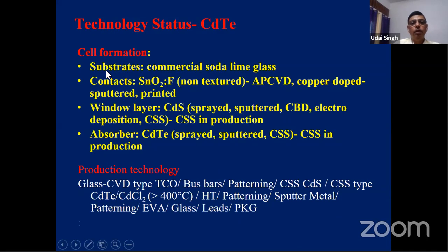So for cell formation, you start with the substrate. Common soda lime glass is used. On the soda lime glass, you have a transparent conducting oxide, which is fluorine doped tin oxide, and it can be deposited by different methods. On top of that, you deposit the window layer, which is cadmium sulfide. Again, it can be deposited by different methods: spraying, sputtering, chemical bath deposition, electro